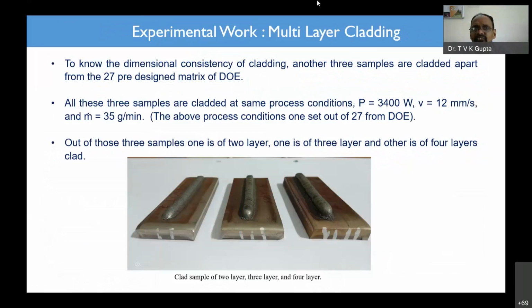Right. So this is the multi-layer cladding, for which we started with the first set of experiments. Based on the 27 experiments that we have done, we considered one process, one parametric set, which we thought would be the best one. For that one we used 2, 3, and 4 layers, the same set of experiments. Then, without changing parameters, we saw how it affects the microstructure and the mechanical properties.